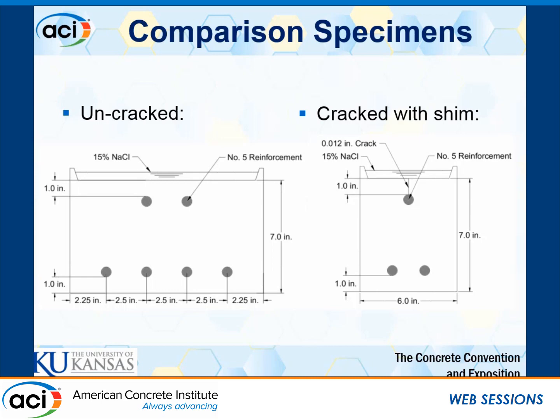Those are cast with a 6-inch long, 12 mil wide stainless steel shim that goes all the way to the surface of that reinforcing bar. It's also important to note that we cast these upside down and flip them over before we start testing. That's so we don't have to deal with or worry about settlement cracking or plastic shrinkage cracking.